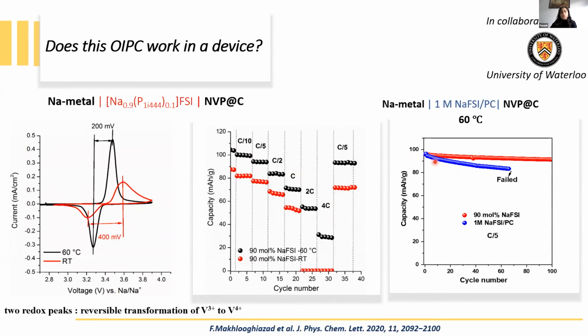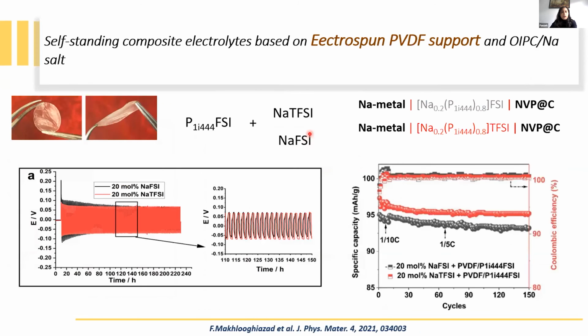And also the cell showed stable long-term stability at high temperature, and in comparison with a commercial organic solvent electrolyte, that is the blue one here, this electrolyte has a tendency to fail, and finally failed at around 60 cycles. So all these results showed that we can use this plastic crystal in sodium devices, in particular at high temperature for some applications that need higher temperature. The mechanical integrity is also very important for the level of their performance.